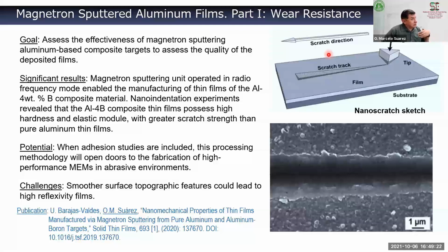Aluminum was soft, aluminum had a low Young's modulus, and so forth. So I recalled that I had done a lot of work on aluminum matrix composites, particularly aluminum reinforced with diboride particles. Could be MgB2, could be AlB2, or niobium diborides. So we were working with an aluminum matrix composite reinforced with aluminum diboride particles. Not nanoparticles, particles, right? Maybe 10 micron size. So we wondered, what if we try to produce thin films with that?